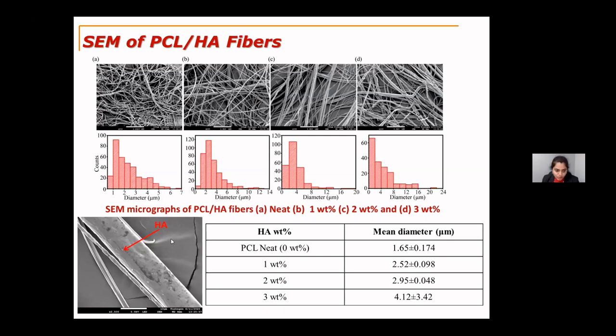Also, I chose to show the fiber at higher magnification here so that we can see the infusion of the hydroxyapatite particles. As we can see here, the small particles over here are all the hydroxyapatite nanoparticles infused into the fibers. So we can say that when we infuse the nanoparticles into the polymer solution, the diameter of the fiber increases. However, if the filler percentage is too high, the fibers are going to be non-uniform and disoriented.